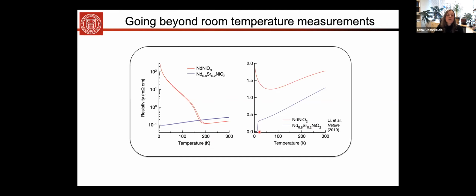Now, the fundamental problem with our measurements is that most of our measurements have been done at room temperature. And of course, we are here today to use cryo-electron microscopy to access these low temperature phases. And for now, I want to focus on phases that we can access using liquid nitrogen cooling, similar to the cooling that you described a minute ago. You will also see that in order to reach the superconducting phase, we need to go to lower temperature.